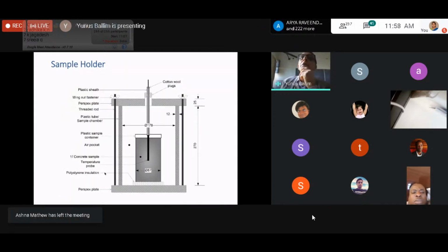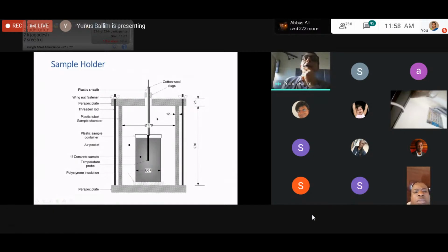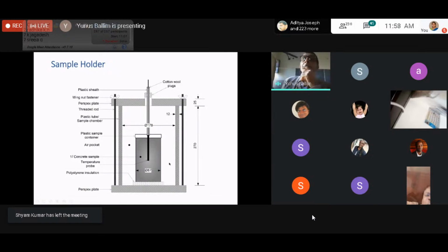This is just a closer view of the sample holder. There's a cotton wool plug here, so we get no pressure development as this air warms up, but we do keep the temperature of the air controlled in response to the water. The sample is sealed inside, and that's how the probe operates.